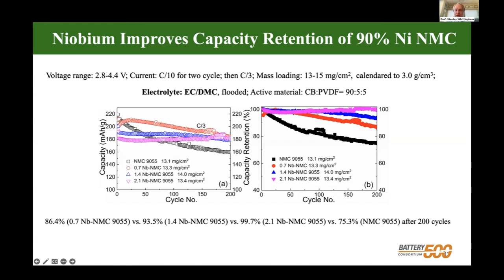And this is just the same data plotted as a percentage. So you can see with 2% niobium in there, we see no capacity loss whatsoever. So niobium is really stabilizing these high nickel materials. And I should emphasize, in this case, we're now up to 90% nickel. So we've gone beyond the 80%. So we can stabilize 90% nickel against reactions in the electrolyte.